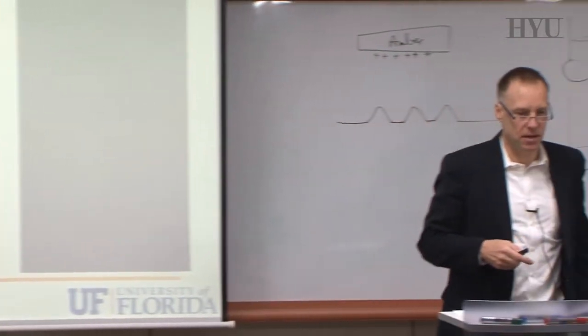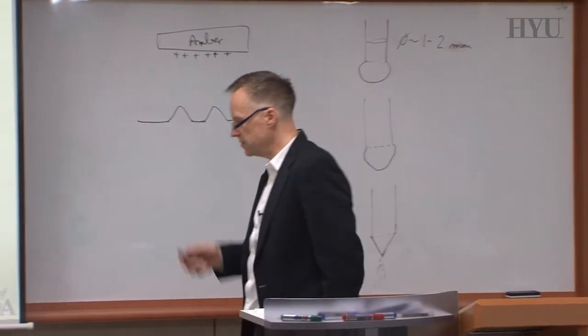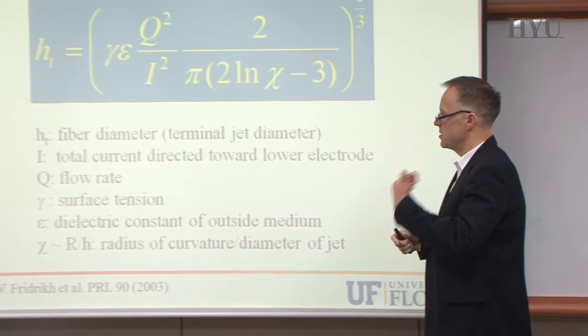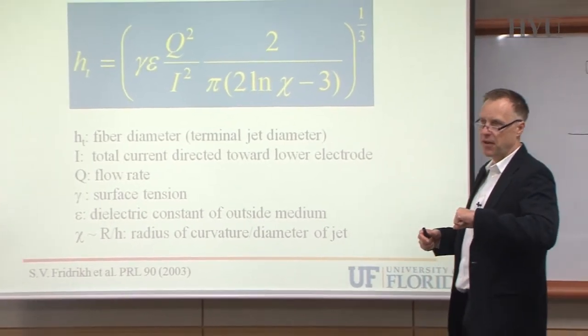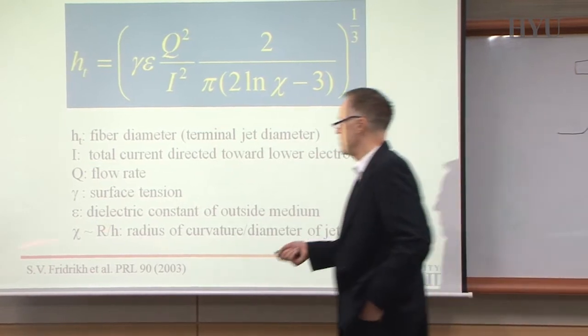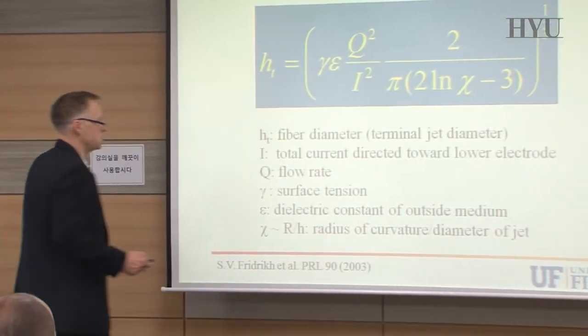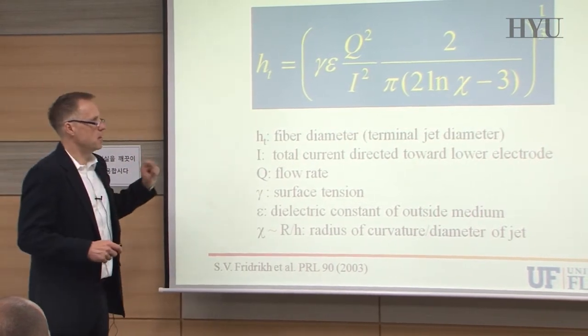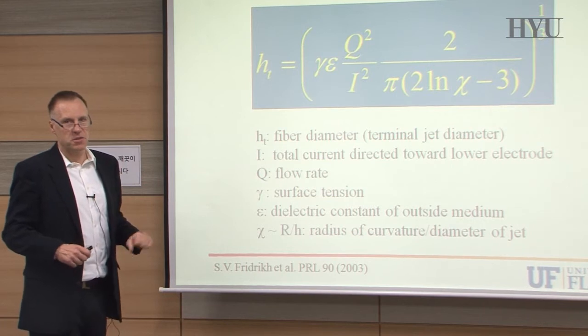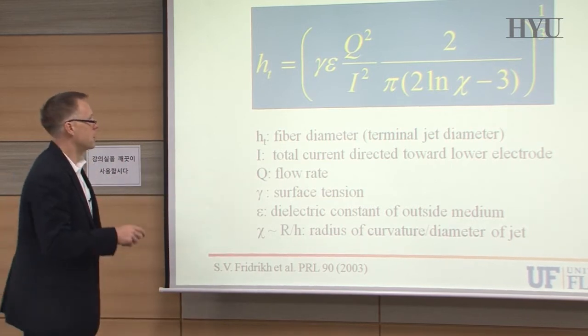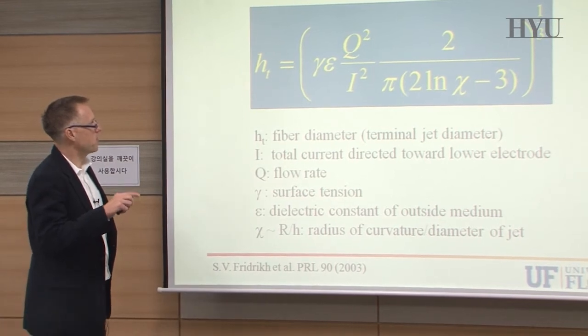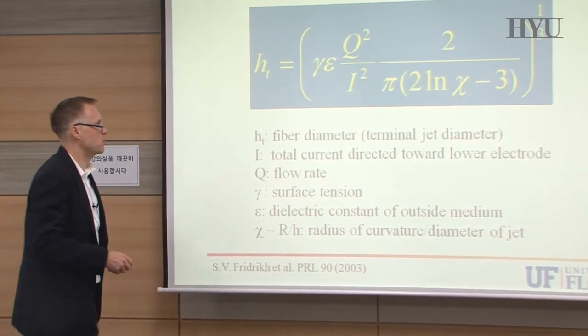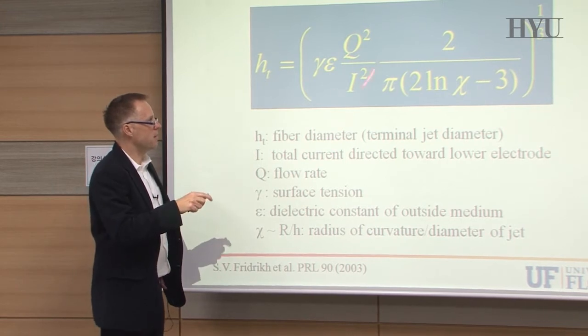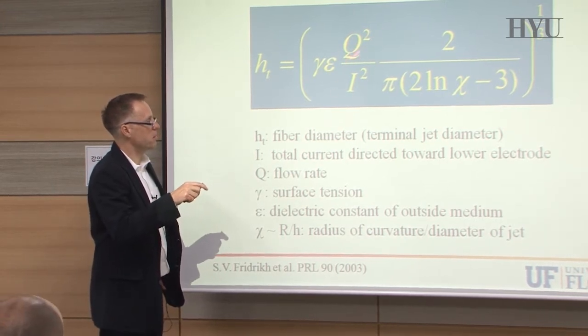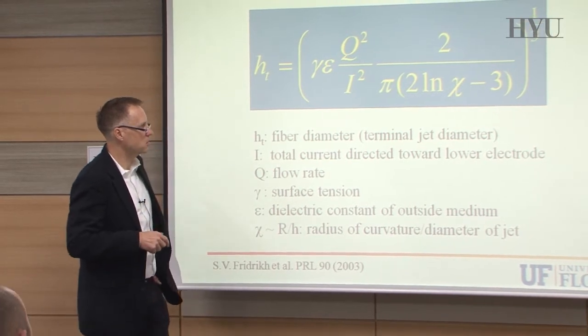But typically there are some other equations that are being used, and that is here. And that is now a system that is based just on the whipping interaction of an electrified jet in an electric field. And that was published by Fridrikh et al. in 2003. So they found that you can actually predict the fiber diameter for a certain dimension and for certain systems by this equation. So the terminal fiber diameter, which means at the end when you deposit it on the surface, is related mainly to the flow rate, how much liquid you pump out, and divided by the current through the fiber. And you see these two parameters are squared, so they're really influential and important.